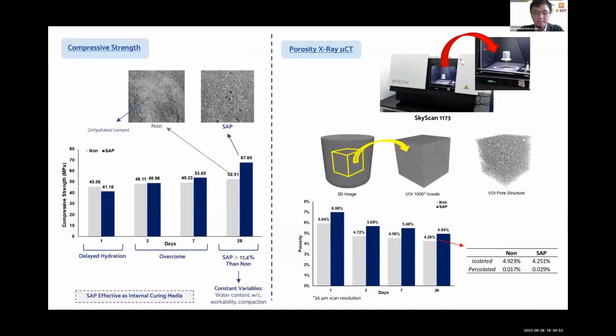For mechanical properties of the specimen, compressive strength test is carried out at 1, 3, 7, and 28 days. In day 1, delayed hydration occurs, which can be attributed to the retention of water in SAP. However, starting from day 3, the compressive strength of the SAP specimen surpasses the non-SAP specimen. This increment can be attributed to internal curing from SAP, which is evidenced by the failure area of the specimen.